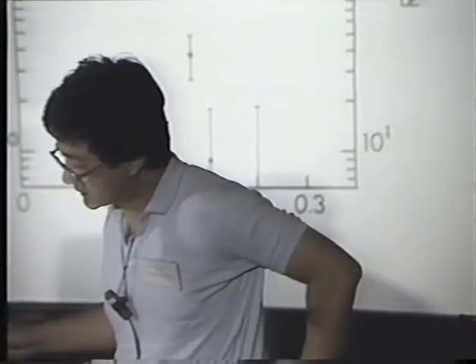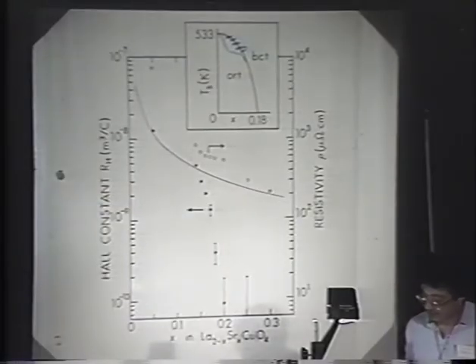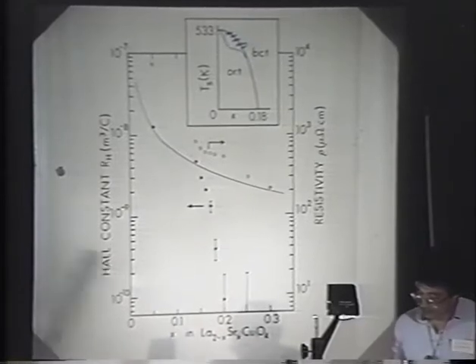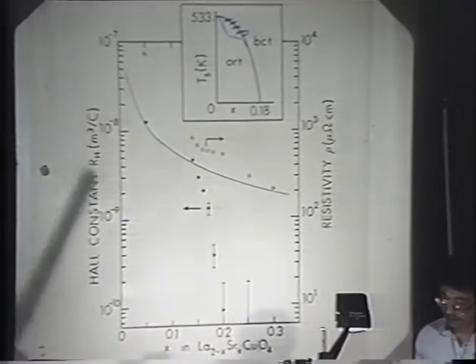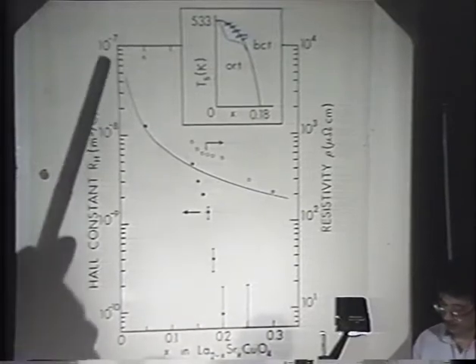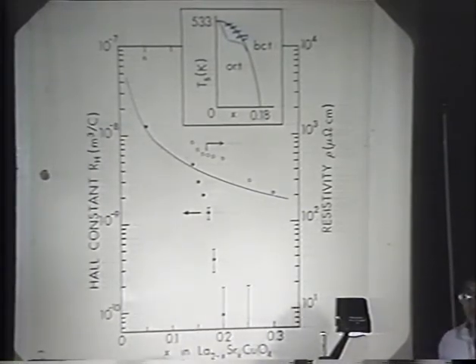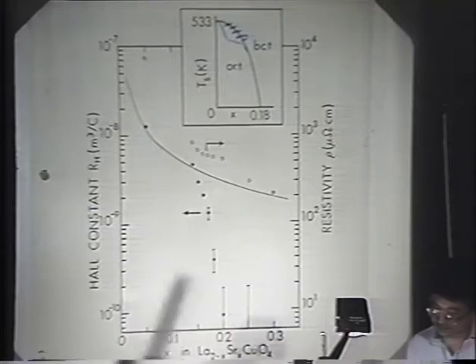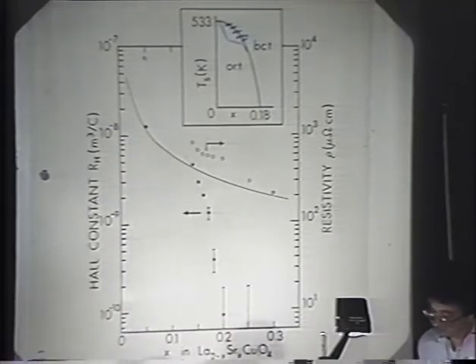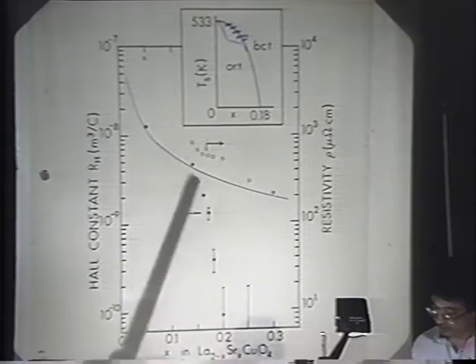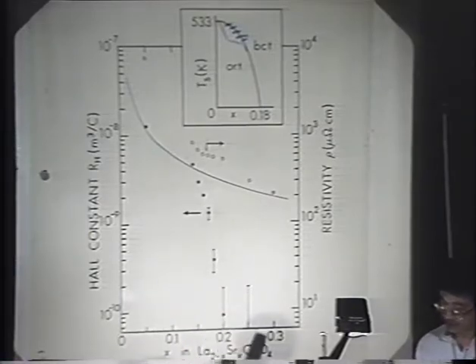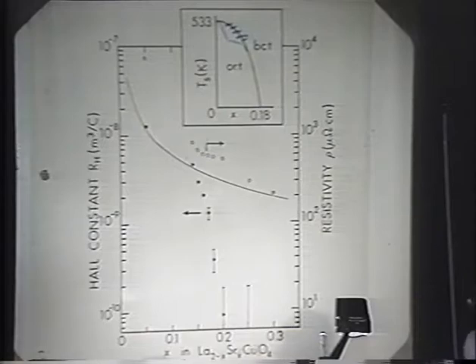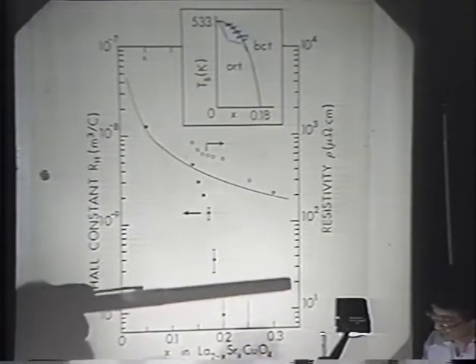The variation is as follows. Let me sort of lead you through this. If you had 1 hole per strontium, then the density would increase linearly, and R_H in a simple band model just decreases as 1 over n, and that's what the solid line is. For the low x samples, this seems to be the rule. Then at the crossover, it rapidly decreases and drops below our level of resolution, which is approximately about this line.